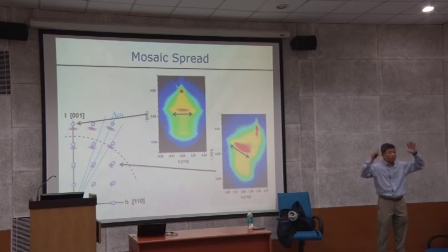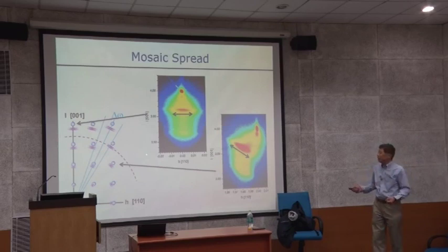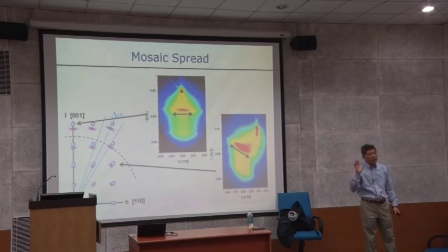So you have to get full two-dimensional or three-dimensional information. There are two ways you can capture this. One way, you scan not only in the L direction, you actually scan slices, many, many scans. With many scans, you actually make a two-dimensional map. It takes this kind of scan, an overnight scan.